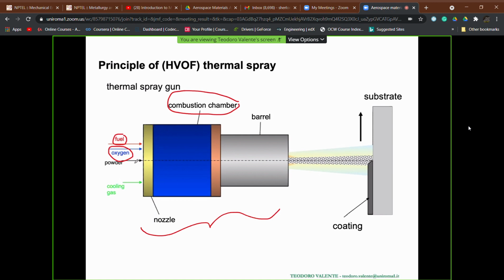Then, in the most common configuration, differently from the plasma spray technology, we have an axial injection of powders inside the gun. And obviously also in this case, we have a gas which transports the powders inside the gun. So we have the interaction between the powders and the high temperature area due to combustion. And then we have a barrel exit, which depends on the gas particle velocity, but usually they are supersonic streams. It has a converging, diverging section in order to increase velocity after the combustion step. Also in this case, the torch usually is cooled, and most of the time it is cooled by gas, not by water, like in the plasma torch.